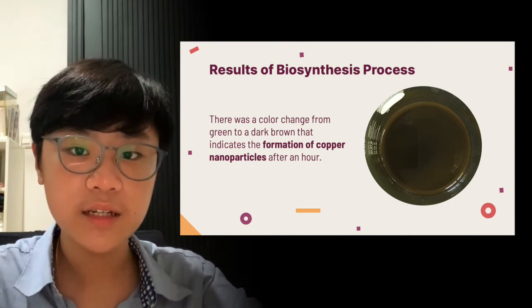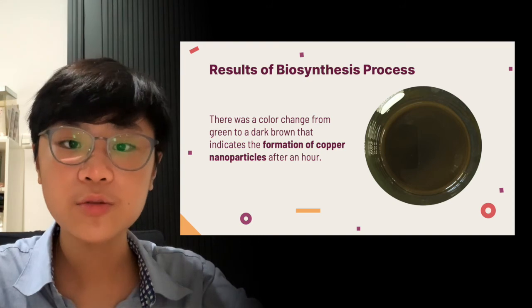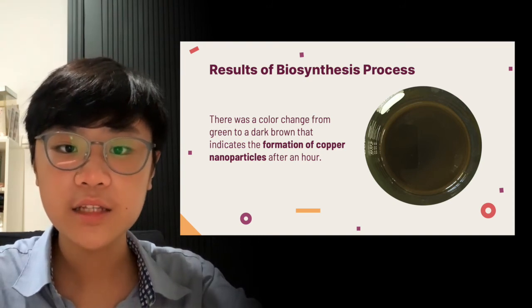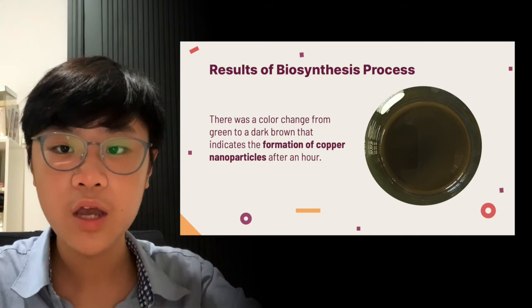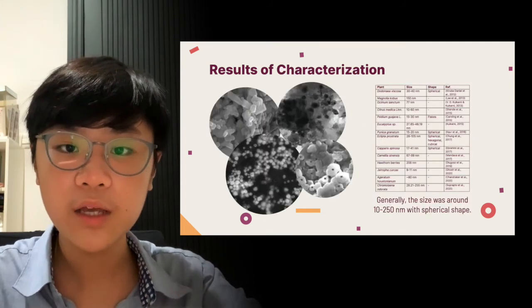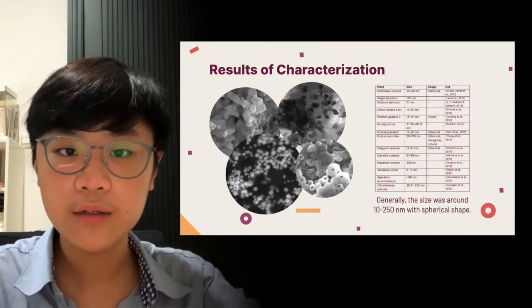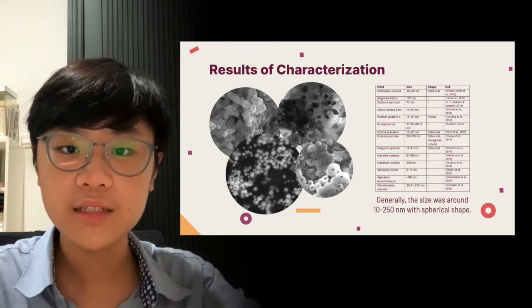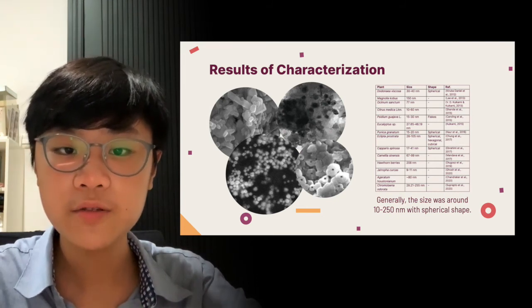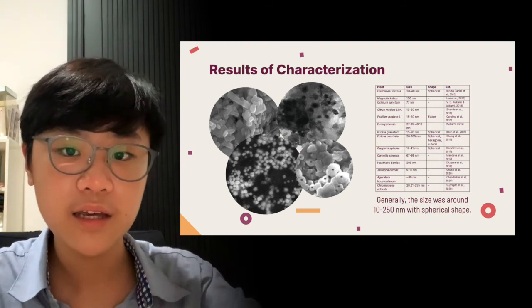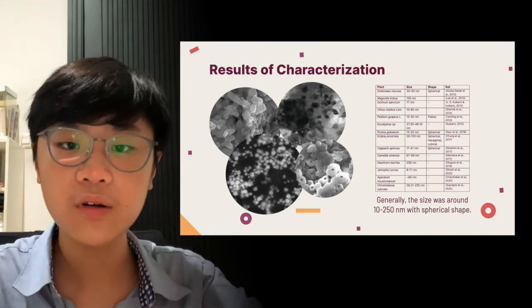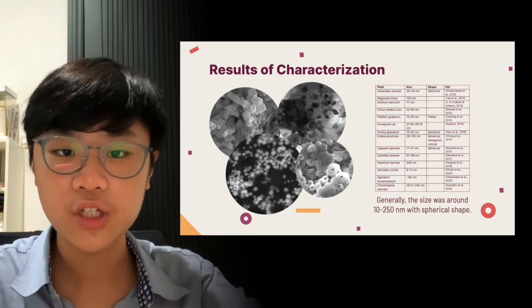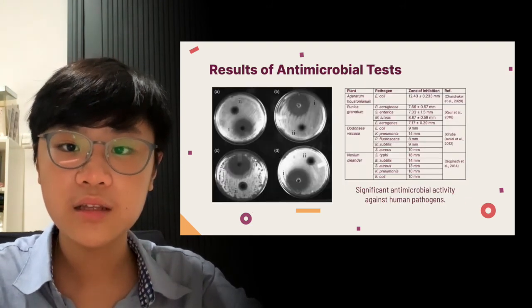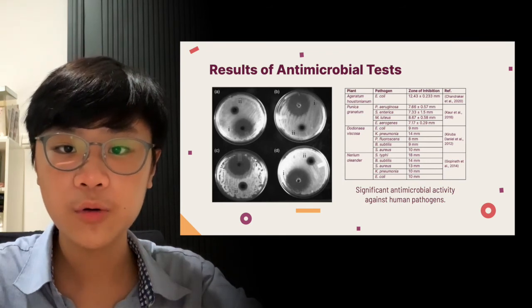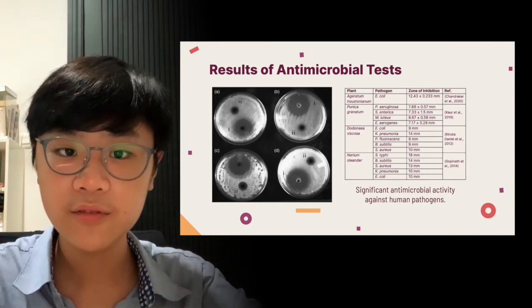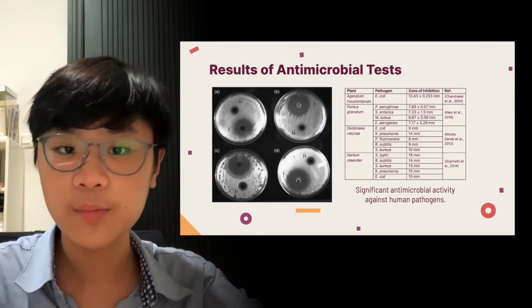Then we have the result of the biosynthesis process. In laboratory testing, there was a color change from green to a dark brown after an hour that indicates that the reaction was complete and copper nanoparticles were successfully formed. Here we have the results of characterization. Here are some examples of SEM micrographs, and the table shows the different sizes and shapes from the biosynthesis with many different types of plants. In general, the size varied from 10 to 250 nanometers with a spherical shape. For the antimicrobial test, the image in the table with the zones of inhibition show the significant antimicrobial activity of copper nanoparticles against human pathogens.